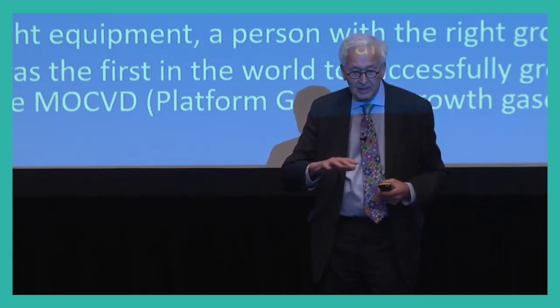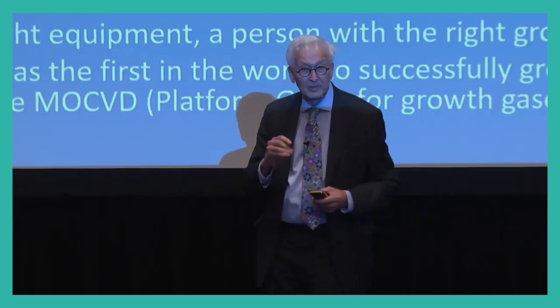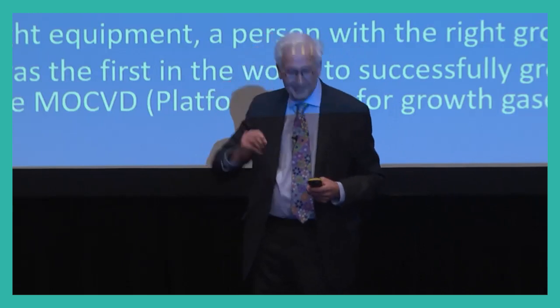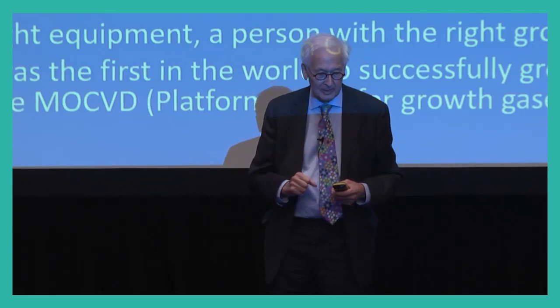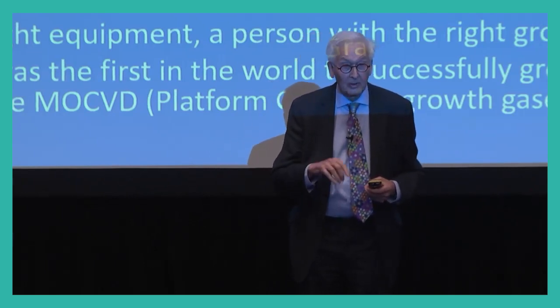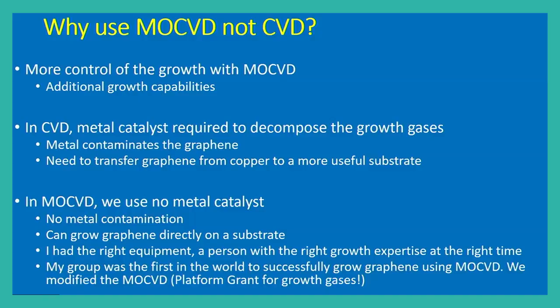And in CVD, you have to use a metal catalyst, as I said, to decompose the growth gases. And what Simon Thomas had was an idea to decompose the growth gases in MOCVD, which didn't involve a metal catalyst. And also you deposited it on the substrate you wanted, so you didn't have to transfer to a more useful substrate. So in MOCVD, no metal catalyst is used, so you don't have that contamination. You can grow graphene directly on the substrate.